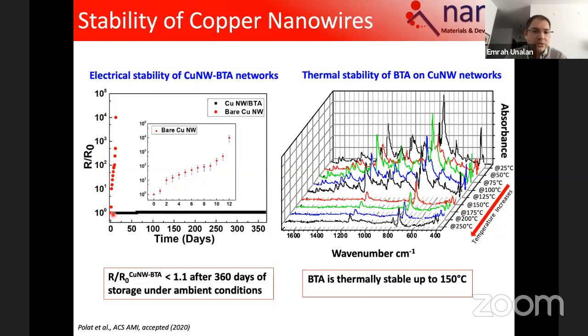And we also made an extensive stability study. As you see, we reported stability of copper nanowires upon BTA deposition in excess of a year, which is not really changing at all in resistance, whereas the unprotected copper nanowires, as you see, diverge immediately after a few days, becoming totally useless. And we also did some very intensive spectroscopic characterization with our colleagues from Bilkent University. We looked into the temperature stability of BTA. It looks like it is stable up to 150 degrees Celsius. This temperature is important. Why? Because this is a very important one for organic electronics processing, which usually doesn't subject these devices to higher temperatures than this. So the BTA is also stable in this regime, which is very promising for us.